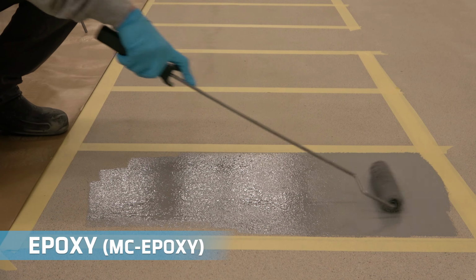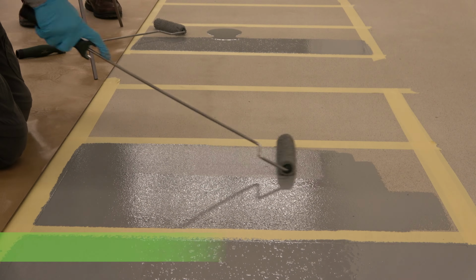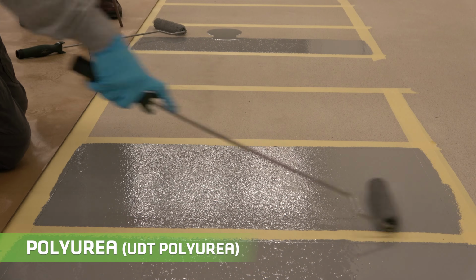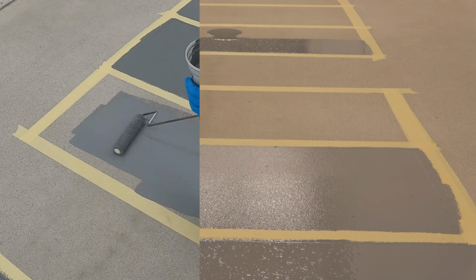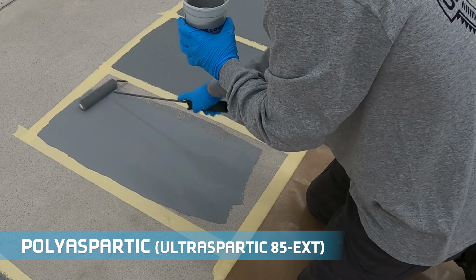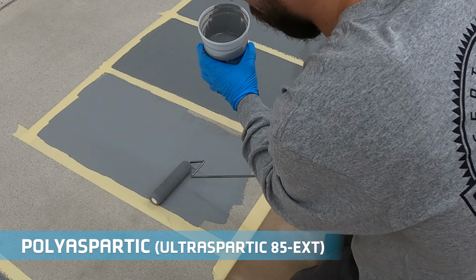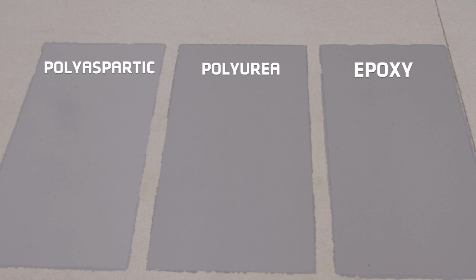We mixed the MC Epoxy, UDT Polyurea, and UltraSpartic coatings according to the directions and immediately applied them to concrete that was prepared to a surface profile of 2 to 3. All 3 coatings were applied at a consistent thickness of 6 mils.